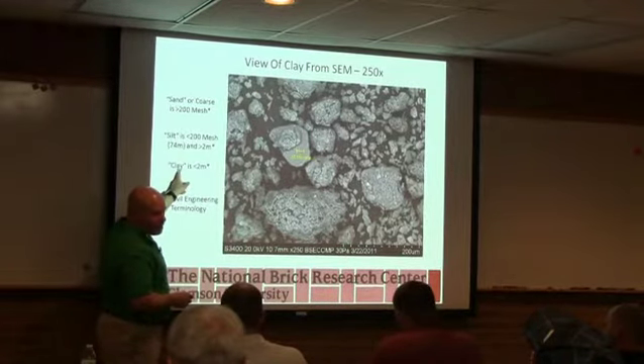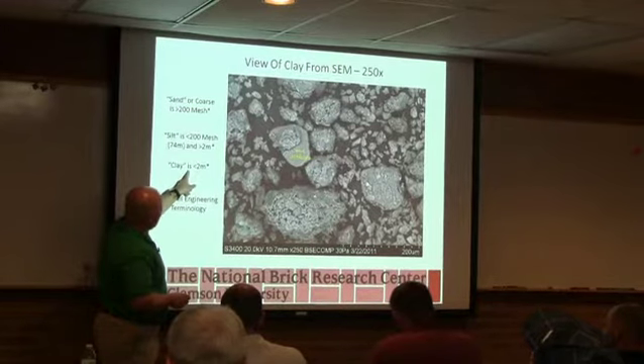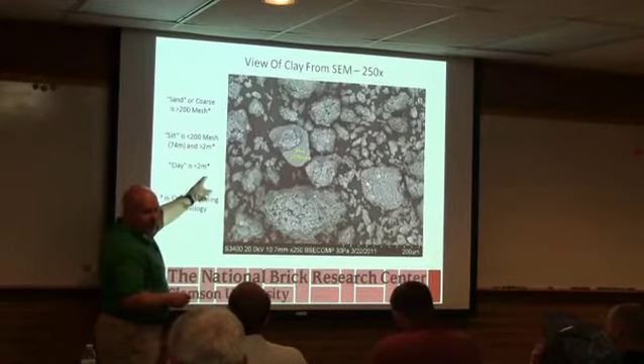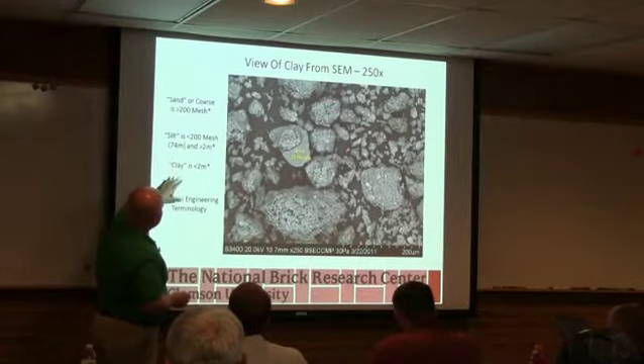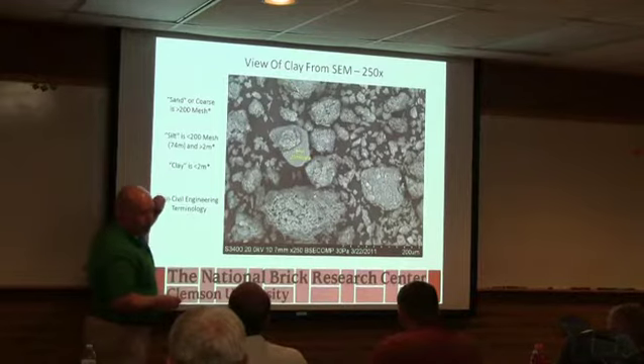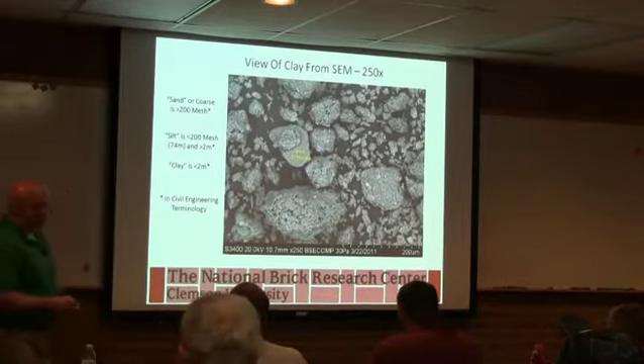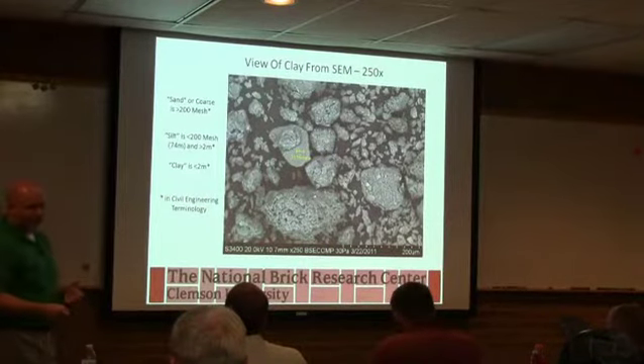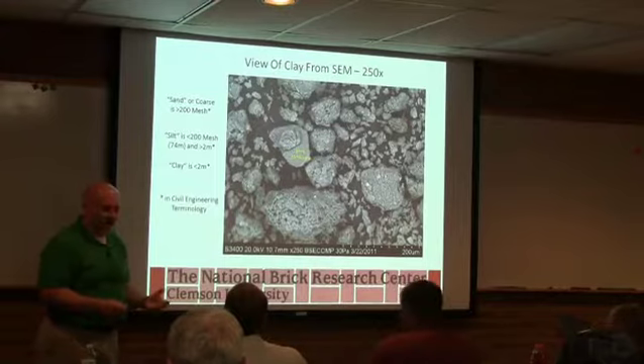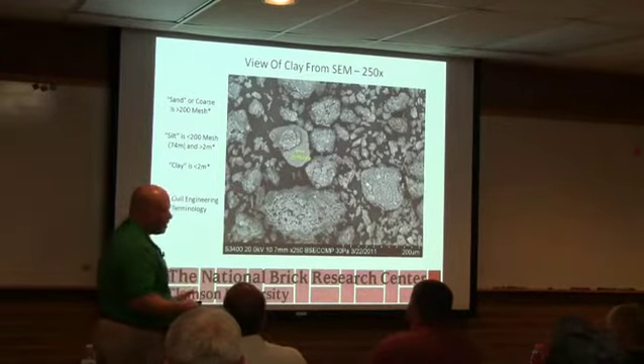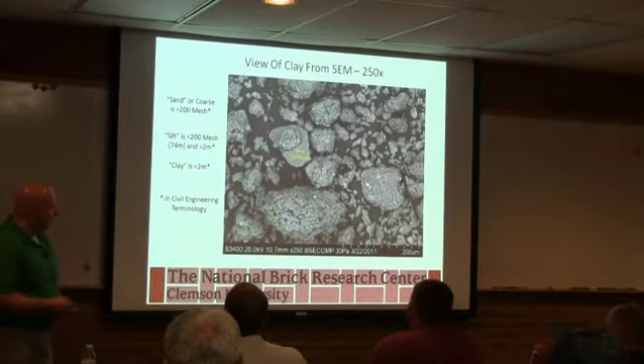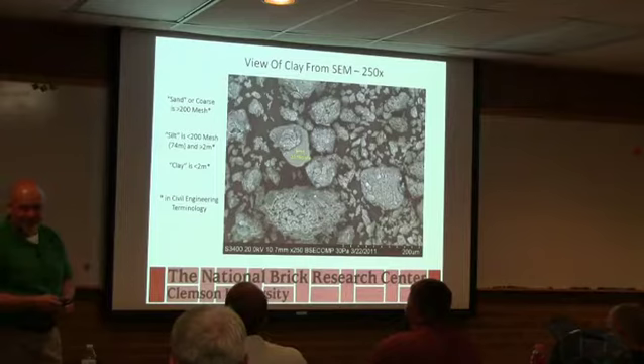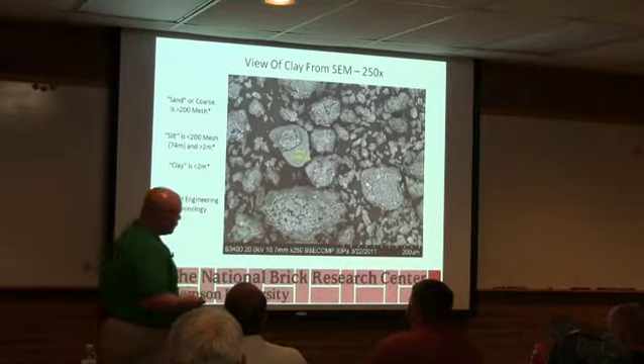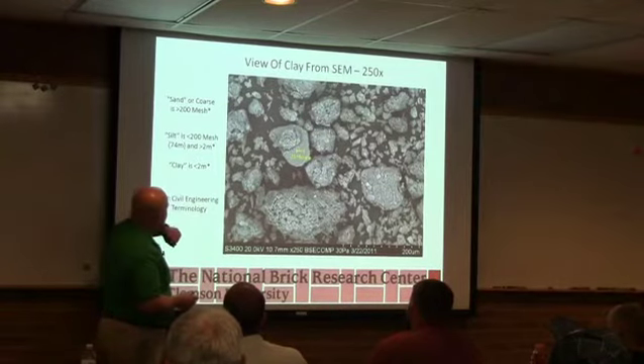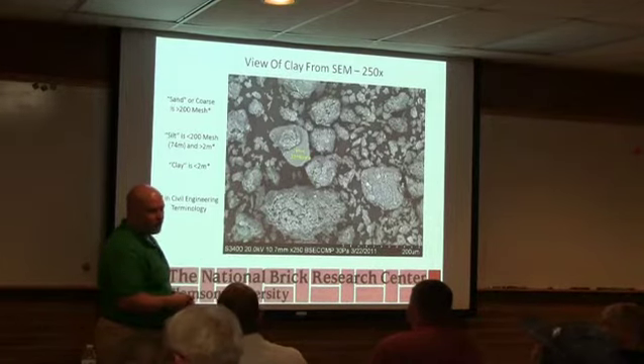Now there are times, raw materials we've seen, where you get a good number for this, but it's not really clay, it's fine sand or something like that. It just happens to be in the size. Those names are strictly to do with particle size. So when you're measuring particle size, the question that always comes up, well, what should I get? Well, what you should get is something consistent that you know how to work with. You don't want to see big variations. A rule of thumb, Jim Frederick, who used to do this with me, he was here last time. I did this probably 10 years ago, I think. You want to be roughly a third of each of your particles. How often do I see that when we're doing particle size? Not very often, okay? But that's just kind of a rule of thumb we're looking for.